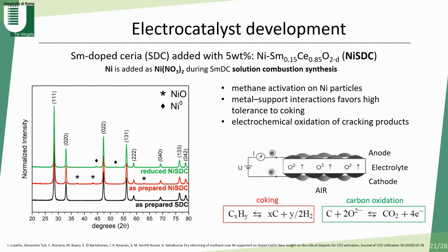So we added 5% of nickel during the synthesis to the samarium doped ceria, which is well known to be a good electrocatalyst. In this compound, nickel behaves as a methane activator. Then the interaction between nickel and doped ceria favors a high tolerance to coking. So this compound was investigated as a good electrocatalyst for oxidation of cracking products in presence of methane mixture.